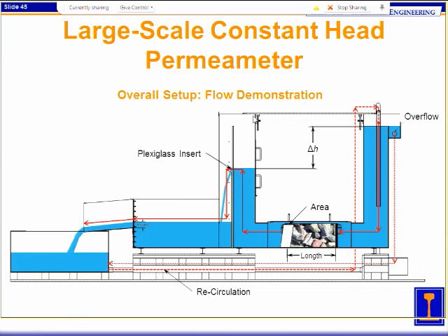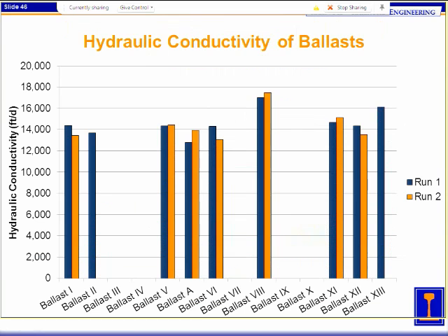If you drop it below about, I know I've tested it about a 9-inch flow height, and it can barely reach this overflow point here, which is what you need to do really to test for that constant head. Comes over here, flows out here. There's a V-notch weir here. That's where we measure our flow height through a stilling well on the side. That's how we get all of our properties there.